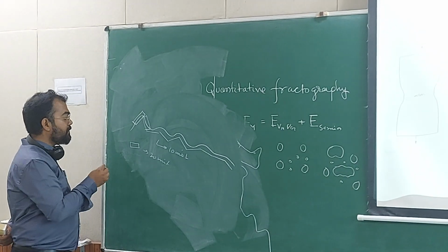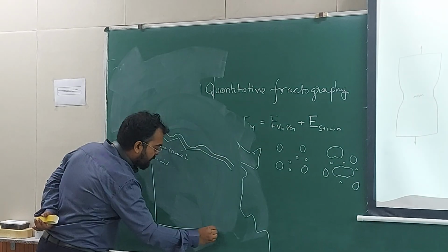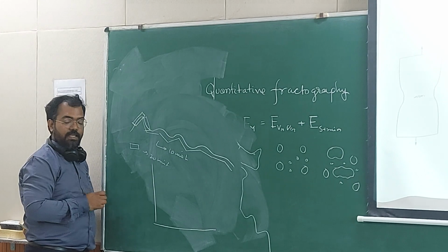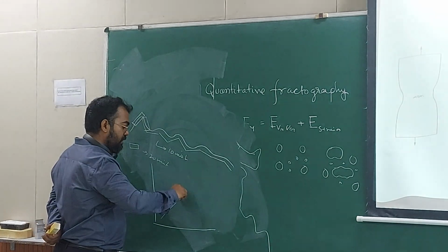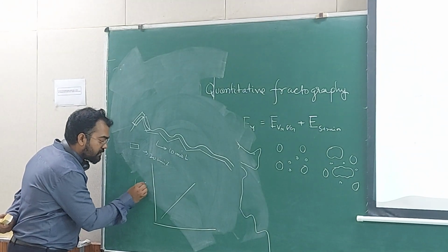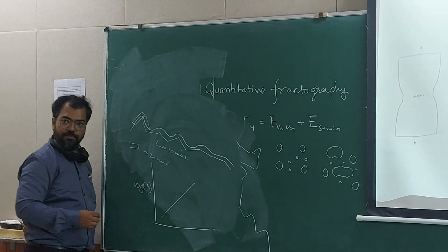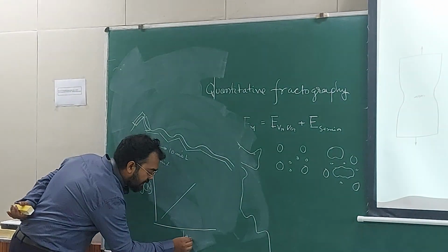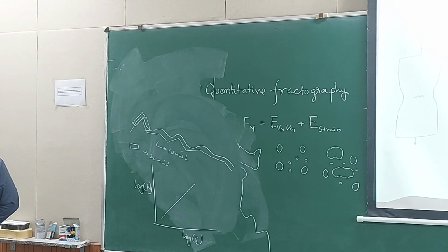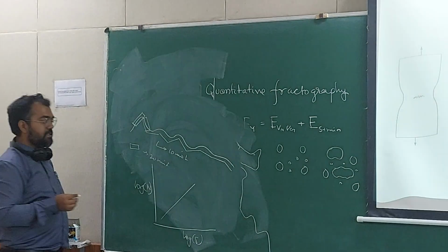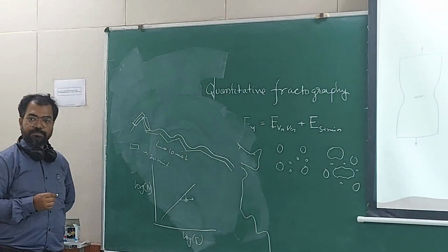So the concept tells that if you choose different scales and you calculate the total length, the log of that will fall on a straight line. So the log of the number of scales you have chosen and the size of the scale you have chosen, that should be a straight line. And the slope of that represents the self-symmetry parameter, which is called fractal dimension.